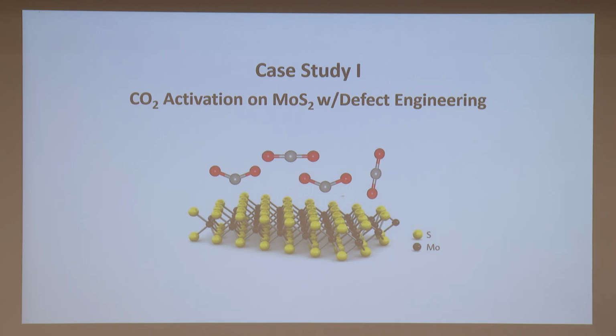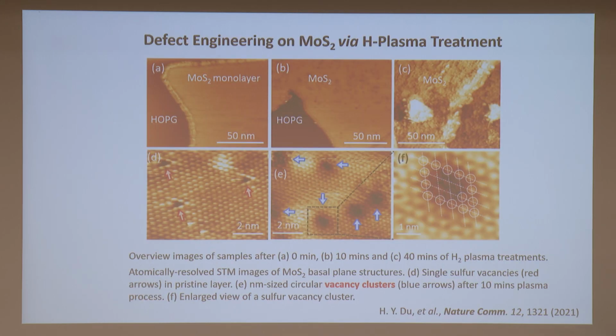So now, why? I showed you the result first. Now you must ask why they would have such an efficiency boost. So first, as I mentioned, CO2 has to come and shake hands with your material. Okay, if it's too perfect, they just don't bother to shake hands. Now we create the vacancy by hydrogen plasma, and this can be directly observed by STM. Okay, without doing anything, the MoS2 produced in the CVD process